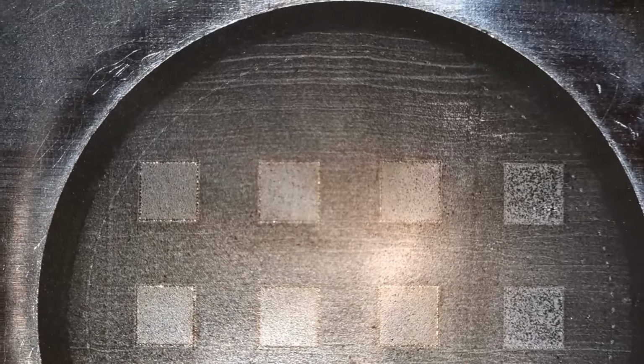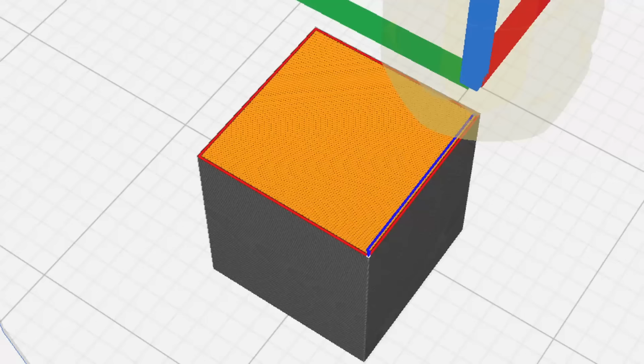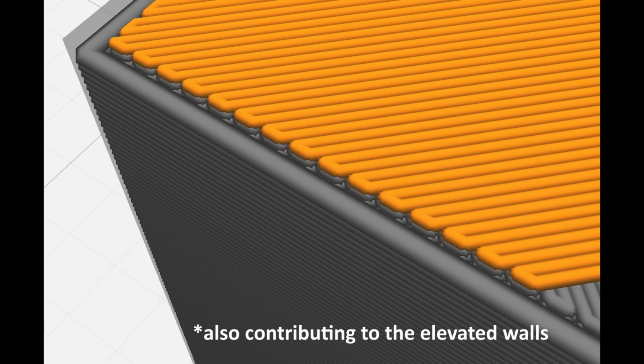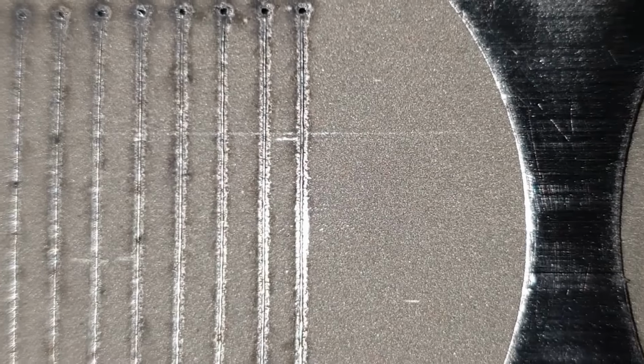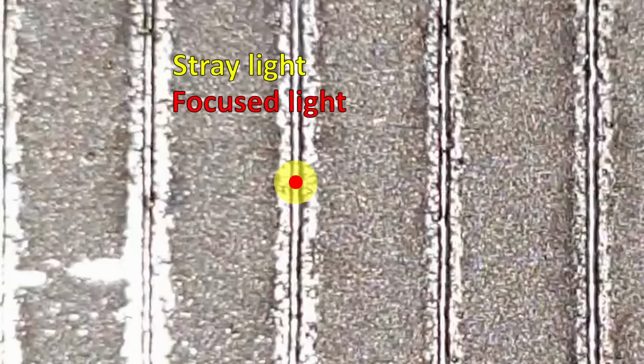The first was that the existence of the walls proved that the processing speeds of the adjoining segments were different to what I had programmed, bound by the processing capacity of the software. The second revelation relates to the very issue I mentioned in the beginning. The causation of the vacancy of powder running alongside the tracks likely had less to do with denudation and more to do with a poorly focused beam.